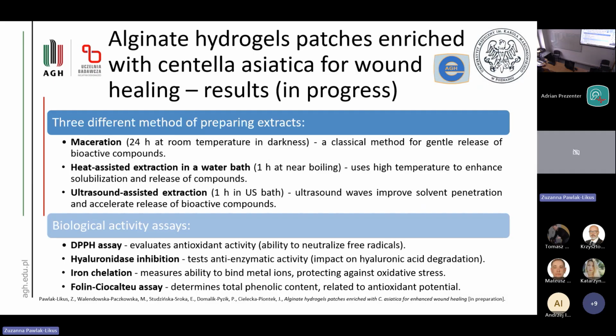a comparison of 3 different extraction methods, and we did maceration. So maceration is a classical method for gentle release of bioactive compounds, and we left our extract for 24 hours at room temperature in darkness. The other method was heat-assisted extraction in a water bath, so we left our extract for 1 hour at near boiling temperature, and this method uses high temperature to enhance solubilization and release of compounds. And the third method was ultrasound-assisted extraction, where we left our extract for 1 hour in an ultrasound bath, where ultrasound waves improve the solvent penetration and accelerate the release of bioactive compounds.